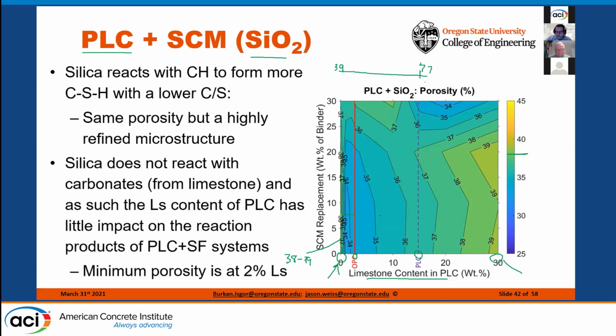The other thing that I'll mention specifically with the silica system: at silica values typically below about 20%, we're still going to have calcium hydroxide in the overall system. You'll see that these contour lines are relatively straight up and down, which means that there's not a huge impact of the silica in the system, right? The silica is going to be reacting with the calcium hydroxide. It's going to form more CSH, right? We're going to have very similar porosity, but a refined microstructure. It's really not reacting with the limestone, not reacting with the carbonates, so it's not going to have a huge impact on the overall porosity. We see that the limestone in general decreases the porosity slightly, but we get very, very similar behavior irrespective of the amount of silica that's in the system.